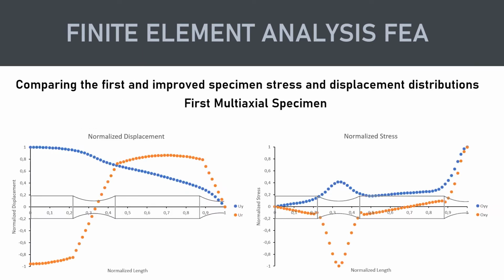Looking at the first tested specimen geometry, we have an equal rotation between cylindrical sections, which leads to an equal shear stress amplitude between throats, and the difference that makes the stress combination higher in the main throat is the axial stress, where it's much higher in the main throat.